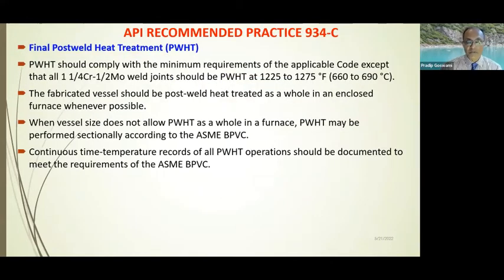Next comes the final post-weld heat treatment. The final post-weld heat treatment of these vessels is typically maintained between 660 to 690 degrees centigrade, that is 1225 to 1275 degrees F. This is a very specific range for these particular equipments. A question may come: what if I exceed that temperature? Generally, you should not exceed that temperature. And if we do the post-weld heat treatment at a temperature below this, we may have issues with the notch toughness, or meeting the impact test requirements for the welds. For the parent material it may not be that much of a problem, but for the welds it is definitely going to be a problem.